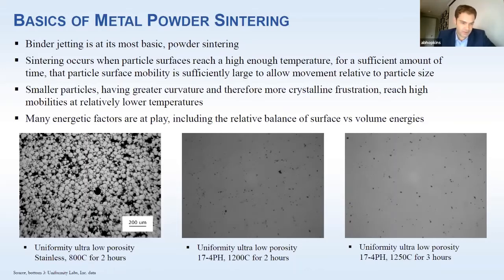800 C for 2 hours is where you start. 1200 C for 2 hours, here's where you go. There's still pores. You can still see the outlines of the larger particles. You can see the size scale here. And then, 1250 C for 3 hours. Now we're starting to get into grain growth and final pore formation. Here you're getting to your 99.5% density. I think, again, this is 17-4. The first picture happens to be 316L, the next two are 17-4.